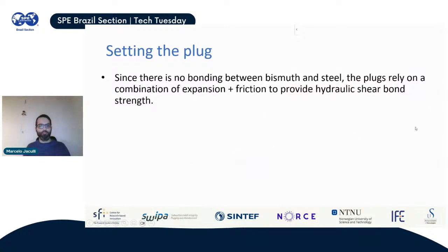But one important aspect here that differentiates it from other sealing technologies and other alternative barrier materials as well, is that there is no type of chemical bonding between bismuth and steel. They are two metals, so they are not going to interact with each other. You are basically setting a plug there by allowing this solidification to happen, and then it will be a combination of the bismuth expanding inside the pipe towards the pipe inner wall, and then friction, of course, because friction is going to happen between the two metallic surfaces.